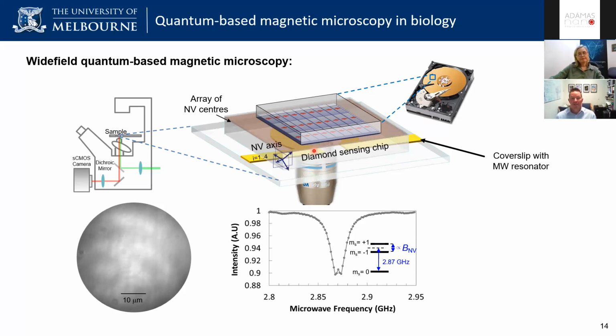At the moment, we're implanting at a density of 10^13 per centimeter squared. When you convert that into effective nitrogen concentration within that small delta layer, it's equivalent to about 100 ppm. So it's really, really high. It's equivalent to the HPHT material. So that's something that we'd like to see come down. If we can start working with chips that have effective densities around the tens to 20 parts per million that are still bright enough for us to image and do this work, that would be fantastic.